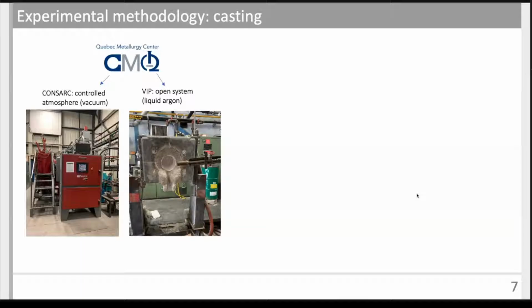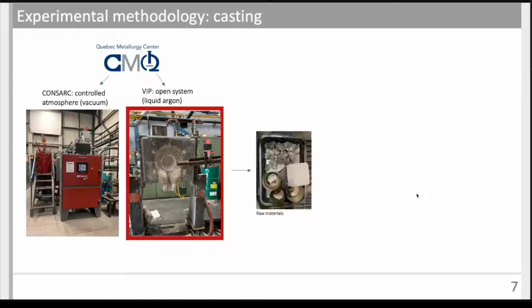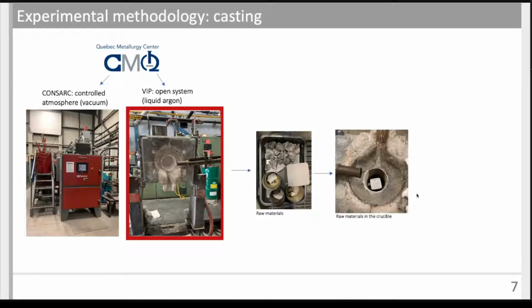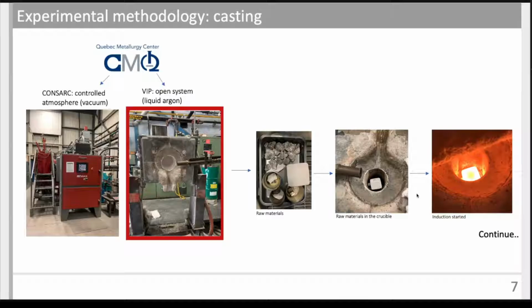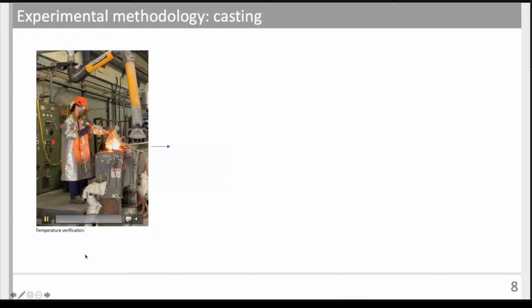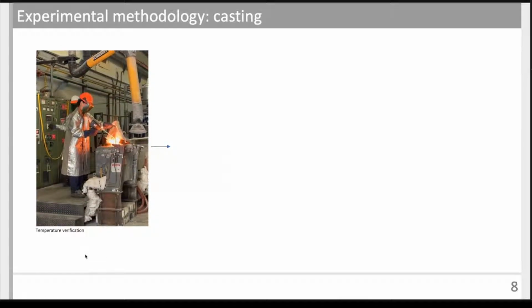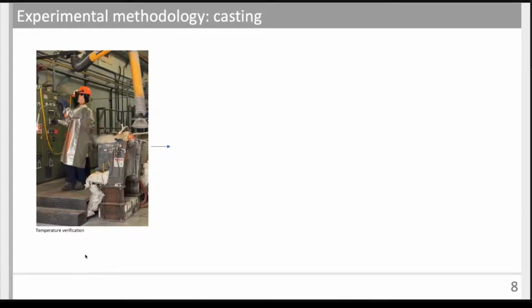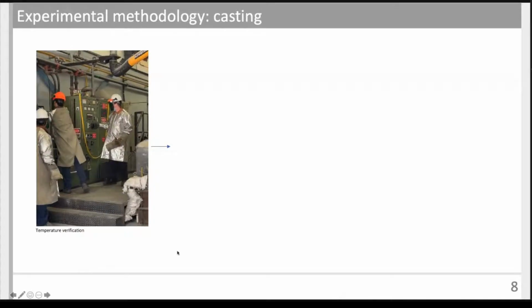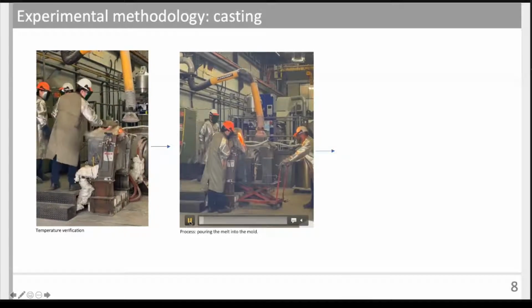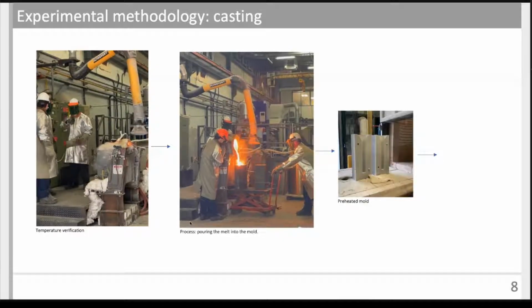And the other one is an open system with a protection made with liquid argon being poured on the top of the melt. So I'm going to focus on explaining the process that we did in the open system furnace. So we weighed the master alloys, and then we placed them in the crucible respecting an order while we started the induction. During the process, we were checking the temperature to ensure that we had reached the minimum temperature to be liquid. And once we had everything melted and well mixed, we poured it into a preheated mold. And then after the solidification, we could remove the bar from the mold. Highlighted here in blue, we can see one of the billets of C6M that were cast in this first trial.